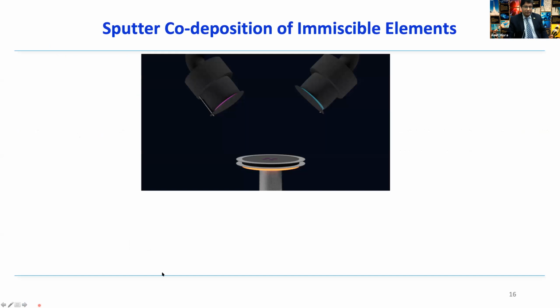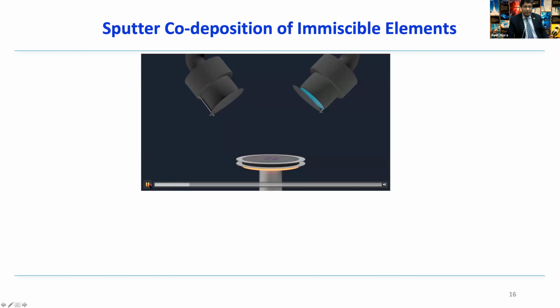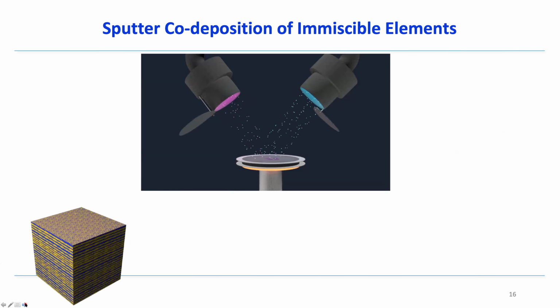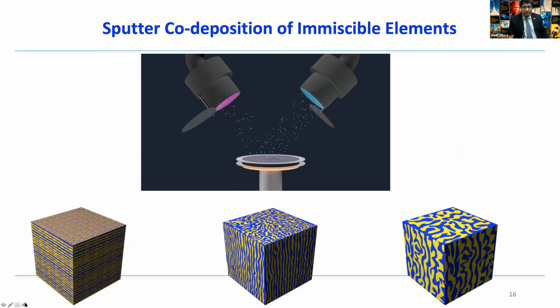And so to make that structure, we are going to use a different approach. Instead of doing a layer by layer deposition of A, B alternating, we are going to mix A and B together. So co-deposition, and do that at elevated temperatures and use elements that are immiscible. So A and B, such as I gave the example of copper, niobium, and similarly, there are many others. If you force these immiscible elements to mix at elevated temperature, there is instantaneous demixing. And that instantaneous demixing can produce other kinds of morphologies beyond just the regular laminate geometry that we get by sequential deposition.